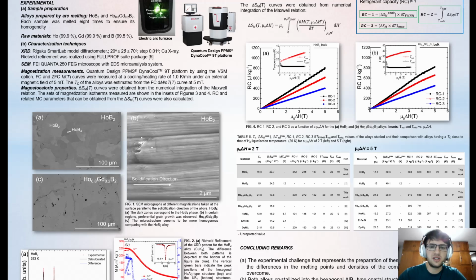From the magnetization measurements under an external magnetic field of 5 millitesla, the Curie temperature of both alloys was estimated, calculating the derivative with respect to the temperature. Regarding the magnetocaloric properties, the magnetic entropy change curves were obtained through the numerical integration of Maxwell's relation using a set of isothermal magnetization data.